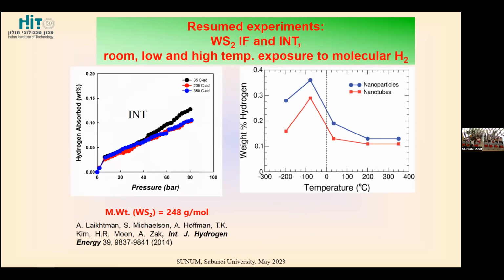So we started with very simple hydrogen exposure, just at high pressure, either high temperature, room temperature, or low temperature. Our first results were not very promising. Though we proved that some hydrogen can be absorbed in these materials, the weight percent was very low. There was about 0.15 weight percent at room temperature, even not so good at high temperature. Though we have to note that the molecular weight of WS2 is very high, 248 grams per mole, while hydrogen is just 2 grams per mole. So very low weight percent still means quite high atomic percent.